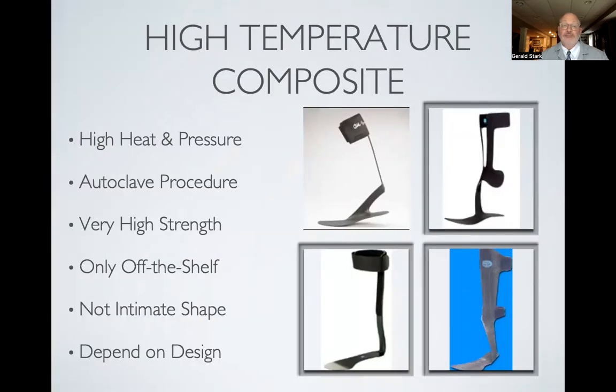So when we talk about high temperature composite, which is really a true composite, the type of composite you have with your fishing pole, it's really with high heat and pressure. The high heat is in excess of about 450 degrees or higher, and usually about 6 to 8 atmospheres. So that's where you have to create a mandrel that's not made of plaster, because once you get above 370 degrees or so of temperature, plaster begins to burn. Have you ever seen that in some of your plaster mandrels? You probably have seen the plaster turn brown. The plaster is actually beginning to burn. So you have to create these on aluminum molds.